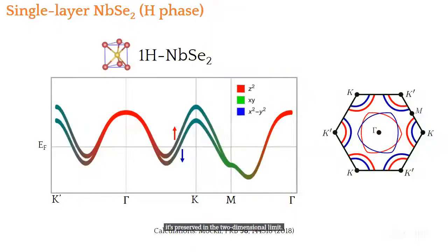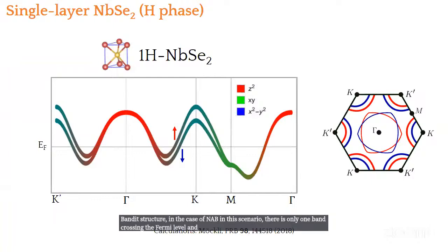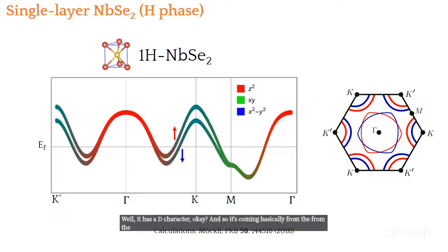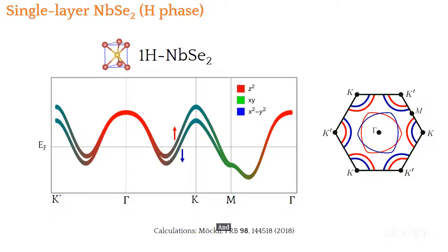And in terms of band structure, the niobium diselenide, or in general, any TMD has a very simple band structure. In the case of niobium diselenide, there is only one band crossing the Fermi level, and ultimately the only band responsible for superconductivity. It has a d character, okay? And so it's coming basically from the niobium atoms. And it has a characteristic spin splitting around the K valley. And the reason is because of the huge spin-orbit coupling in the monolayer limit.